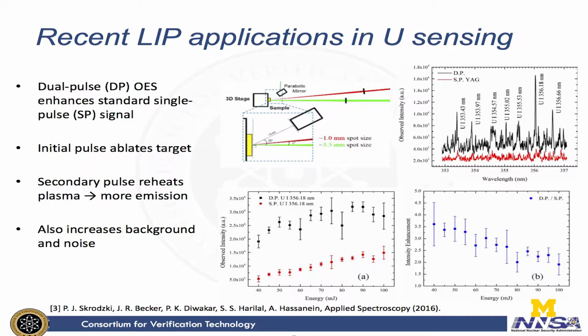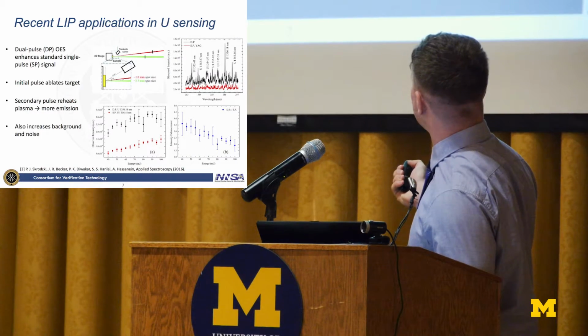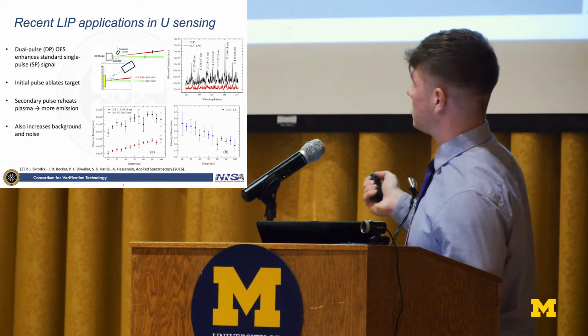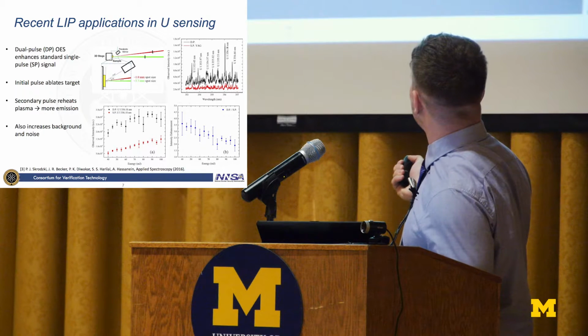Some other more recent work that I've done personally, using a dual pulse laser ablation technique to increase signal. Here is an example of the resultant spectrum. So the standard single pulse is shown in red, and the dual pulse significantly enhances the signal and stimulates the emission of particular uranium species shown in the black.